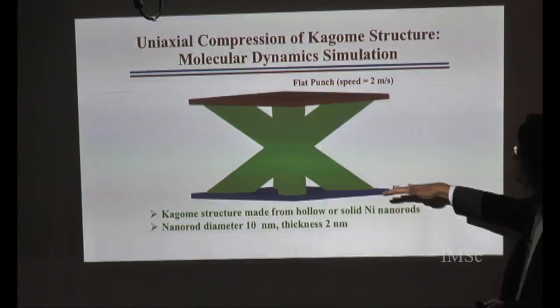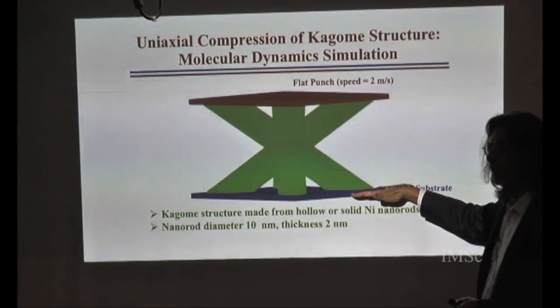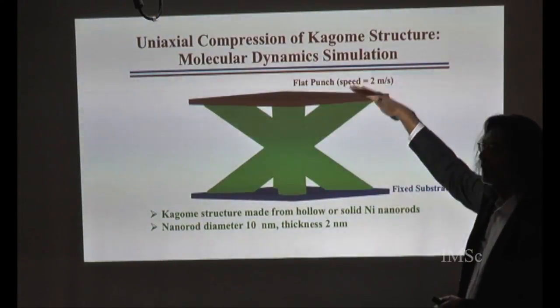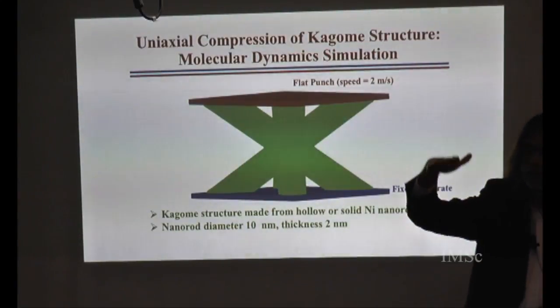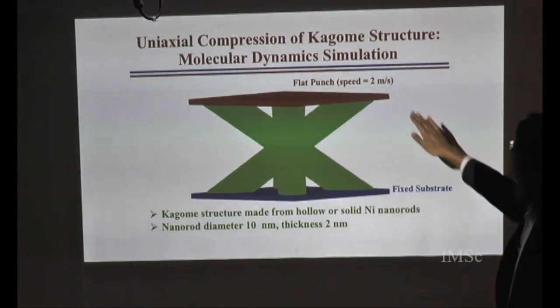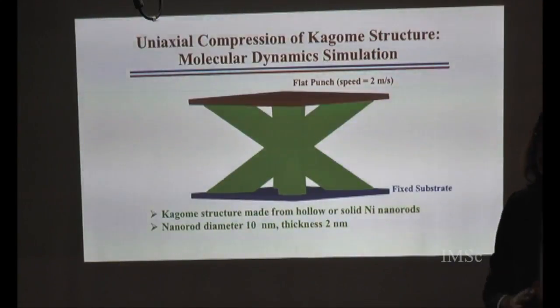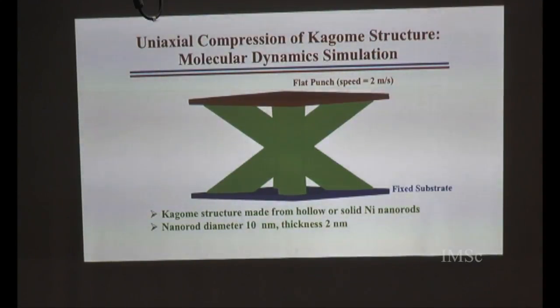These things are sitting on a substrate, and then we do a flat punch. So we push the punch. The speed is 2 meters per second. Of course, our rates are much higher, and that's our limitation in simulation. And so I will show you what happens to this system.